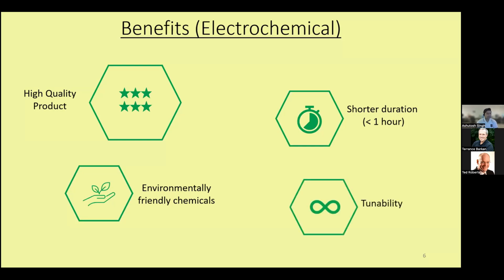We also have a slightly additional value here. Since we are doing an electrochemical process, during the oxygen evolution between the layers of the graphite, some of these graphene flakes get oxygen functionalized at the edges. If you imagine my palm as a graphene flake, the oxidation happens at the edges. So you get certain oxygen functional groups, which act as a so-called surfactant and make the graphene very nicely dispersed in water, which is essential for several applications that we discussed with our customers and partners. In addition, we also get certain heteroatoms doped into the graphene structure, which we will talk about in later slides.